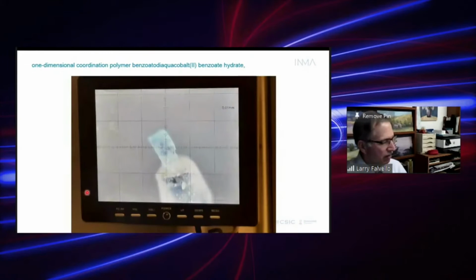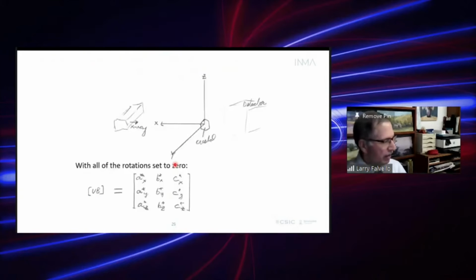So the general procedure is you line up a crystal on an X-ray diffractometer. Here is a crystal on an X-ray diffractometer. This is not one that was used for magnetic measurements. But anyway, the diffractometer gives you an orientation matrix, and that relates the components of the reciprocal vectors, A star, B star, and C star, to a local reference frame on the diffractometer, which is Cartesian. So now I have a very good and accurate description of the crystal orientation.